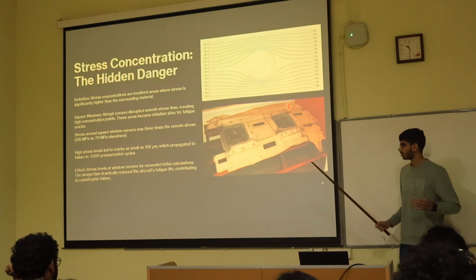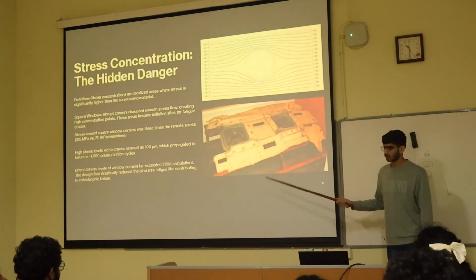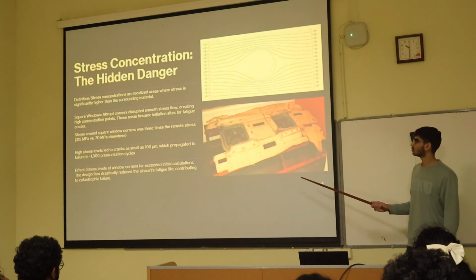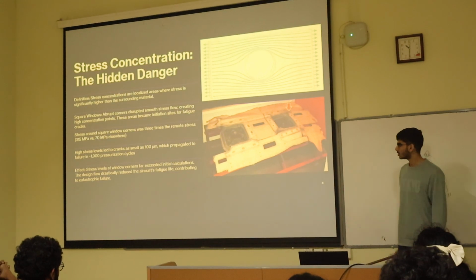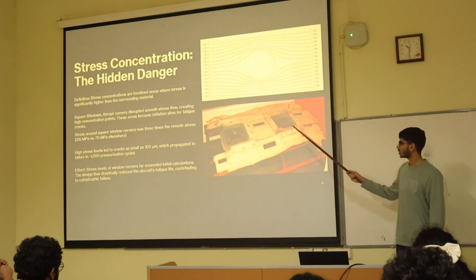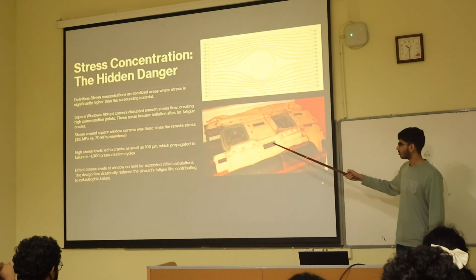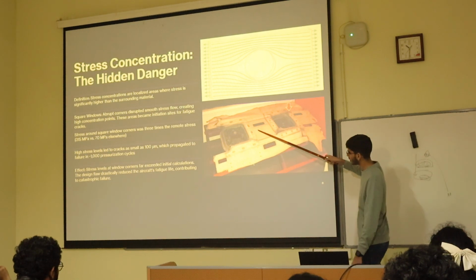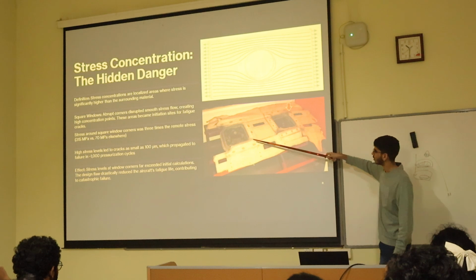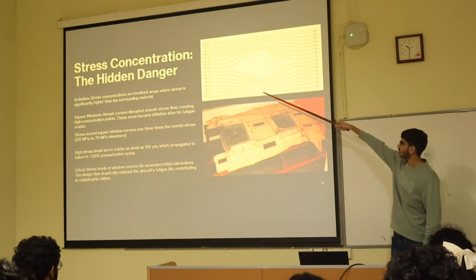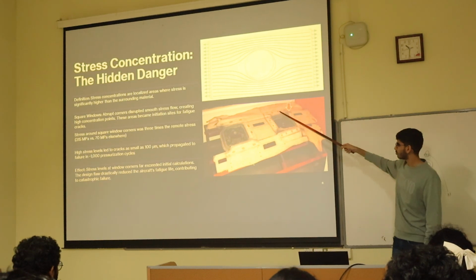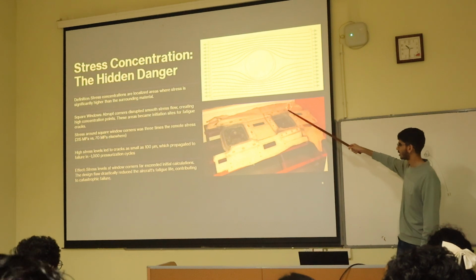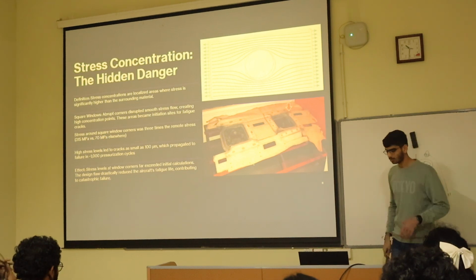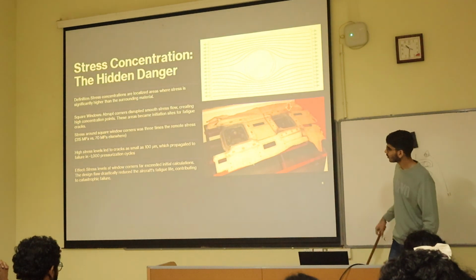After they found out that the plane had exploded mid-air, these were the conclusions they came to. The first fatal flaw was the stress concentration. Because of the square windows in the de Havilland Comet aircraft, there was stress concentration around the cracks, around the edges of the windows. If there are circular windows, the flow of stress is quite uniform, but because of the square windows, the stress concentrated here may lead to even more cracks and more fatigue.